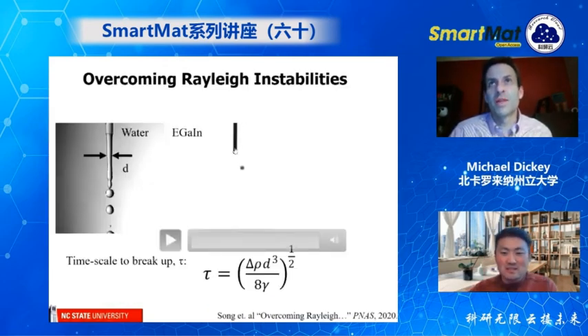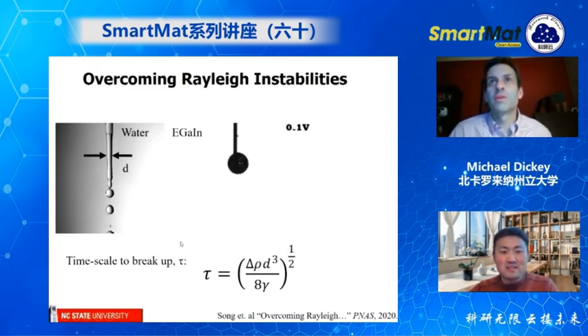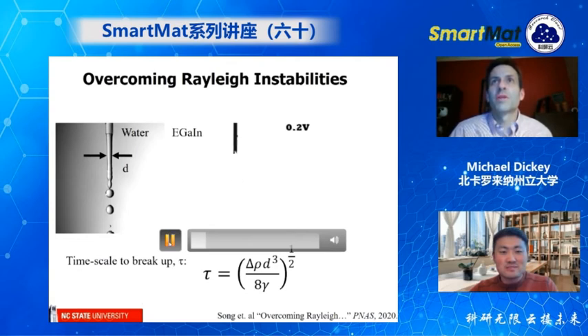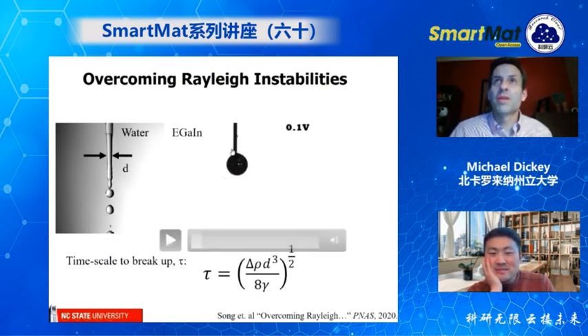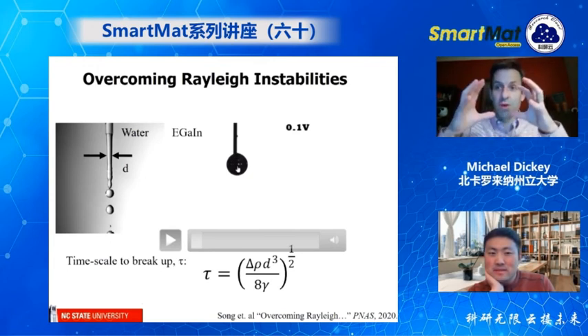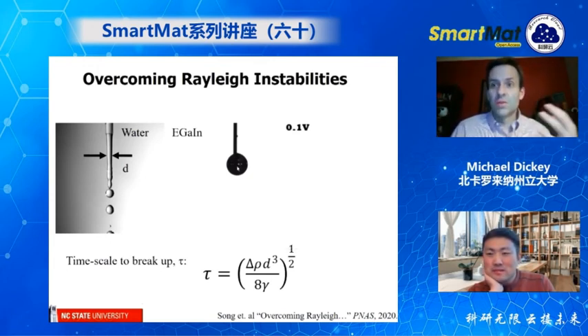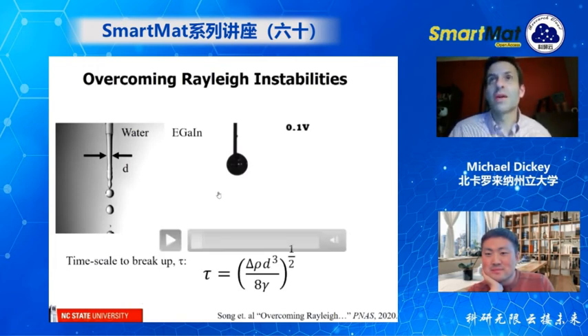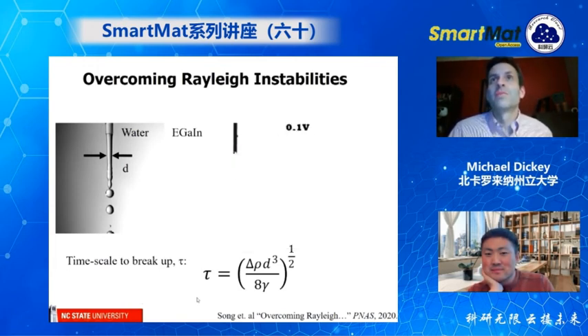The diameter of this nozzle is 100 microns, so it's actually quite small. And when you pump it out, you see, let me pause it if I can. Right there. This droplet is staying on the nozzle because of surface tension, and it will get bigger until gravity causes it to fall. So there's a balance between surface tension and gravity, and we've quantified that. I don't have the data here.